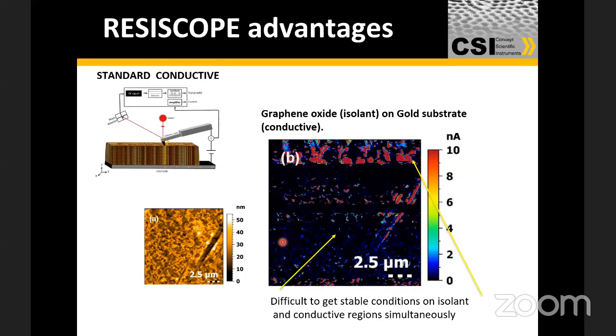And this is one such illustration, I guess. You can see that this is actually graphene oxide again on a gold surface. And we're trying to illustrate some of the classical differences, the difficulties in making the measurement. If you look at the image here, the bottom of it gets pretty dark because of the problems that I just explained. It is difficult to get these stable conditions on the graphene oxide isolates and then be able to measure their currents, precisely because of the same problems.